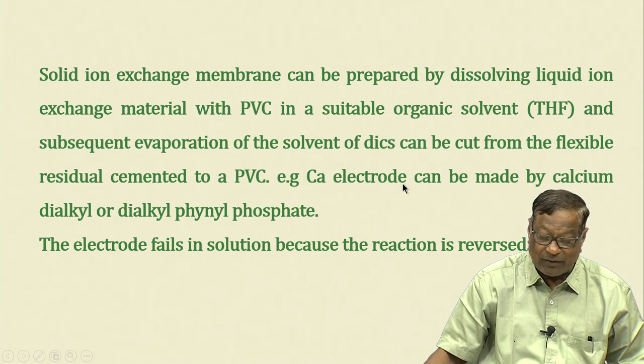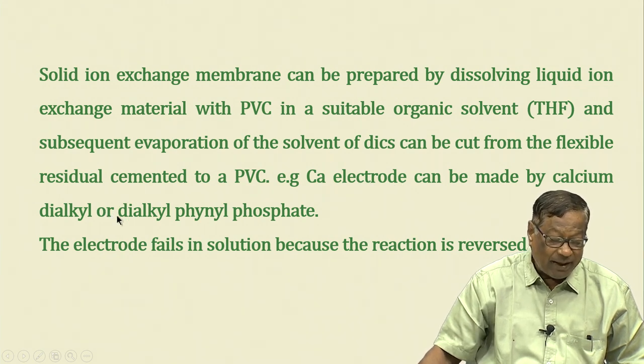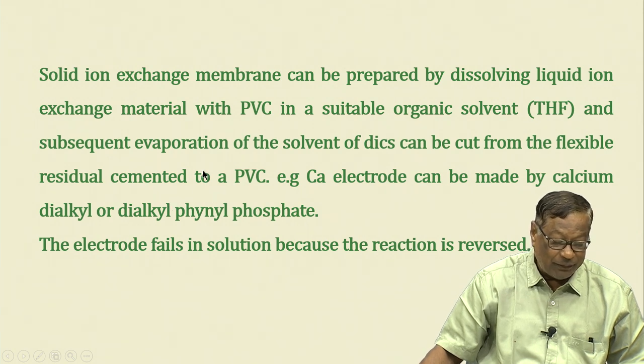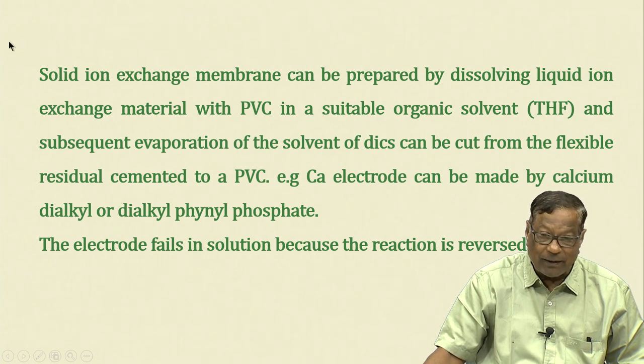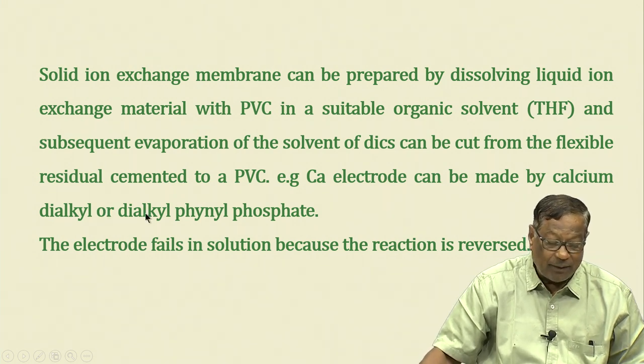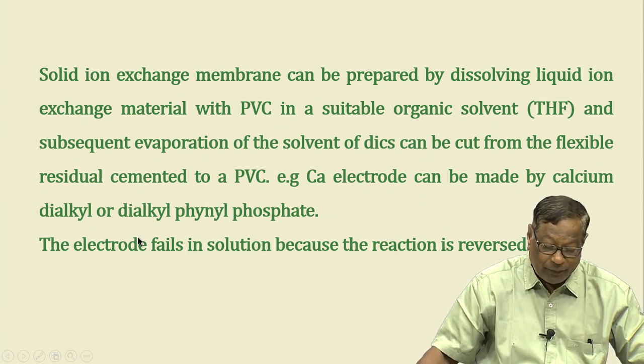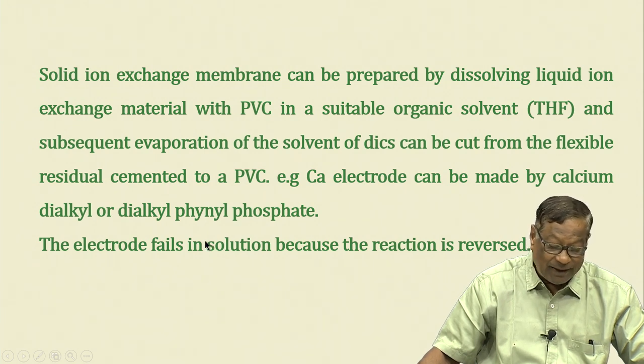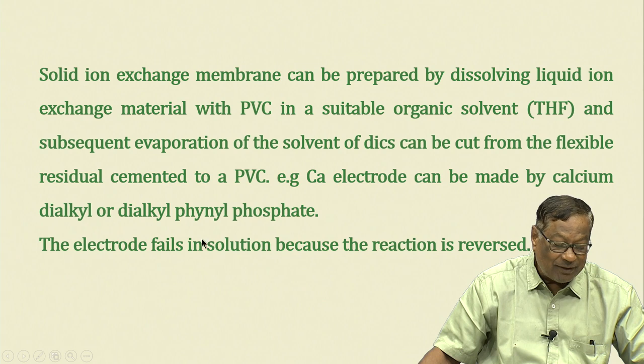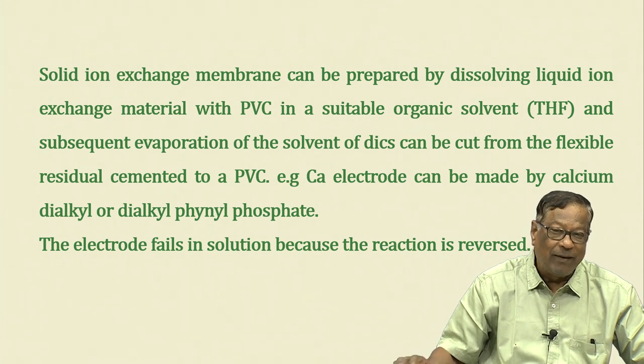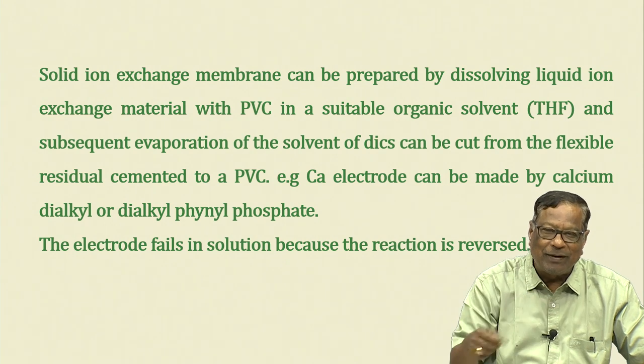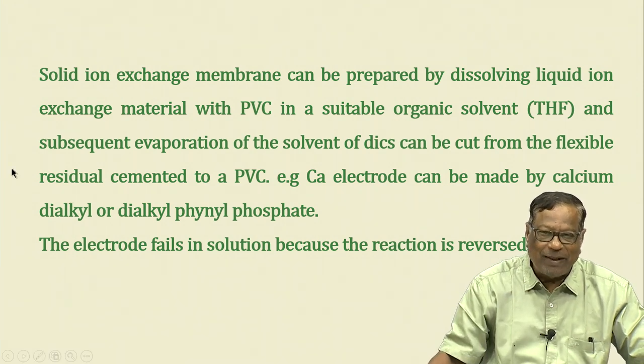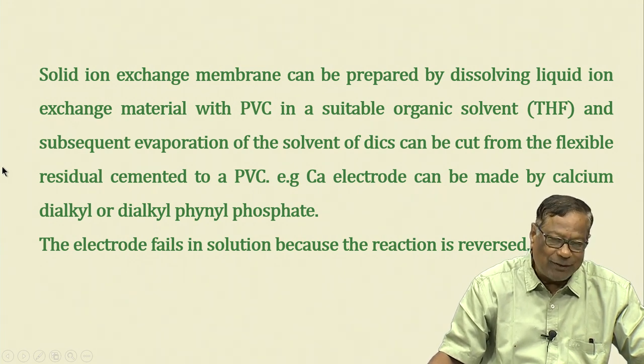So I can have a calcium electrode. It can be made from calcium dialkyl phosphate, or simply dialkyl phosphate, or dialkyl phenyl phosphate. So this is the liquid ion exchanger material. But the electrode fails in solution because the reaction is reversed. Sometimes such electrodes we do not want, because if the concentration is very low, then the calcium ions can move out from the ion exchanger into the solution. So that danger is always there. So one has to be a little careful whenever we use liquid ion exchange electrodes.